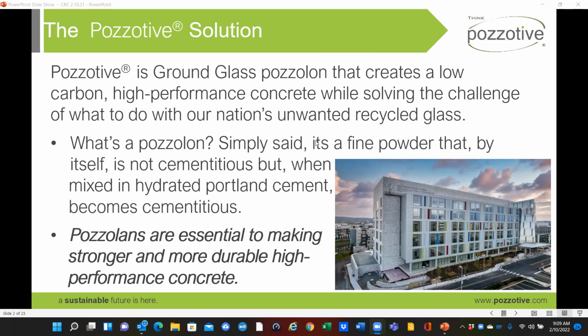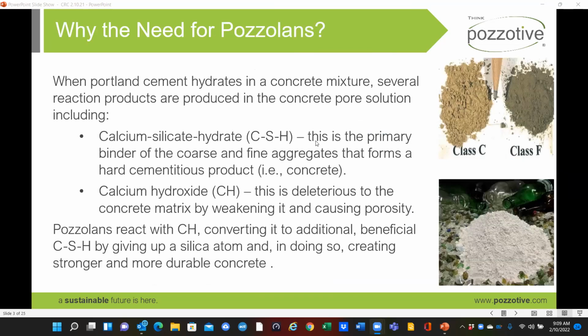And pozzolans are essential to making stronger, high-performance concrete. And that's why it's so important to our DOTs around the country. Not to belabor the science part of this, but just for the science geeks in the group, two things happen when you make concrete. The good stuff is made, calcium silicate hydrate, which is basically the glue, the binder, if you will, of the concrete mix. The bad thing that occurs is calcium hydroxide is created. It has a deleterious effect on the concrete mix when that chemical reaction occurs.